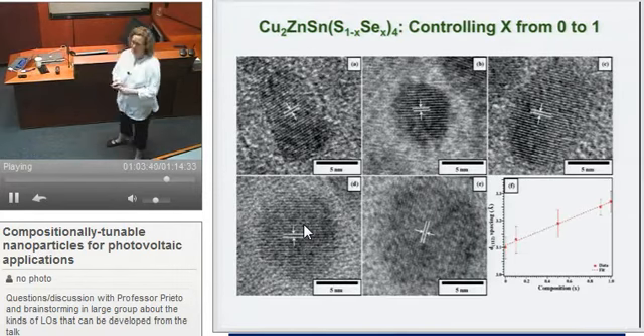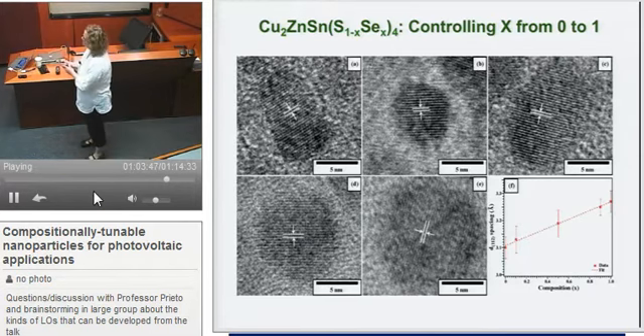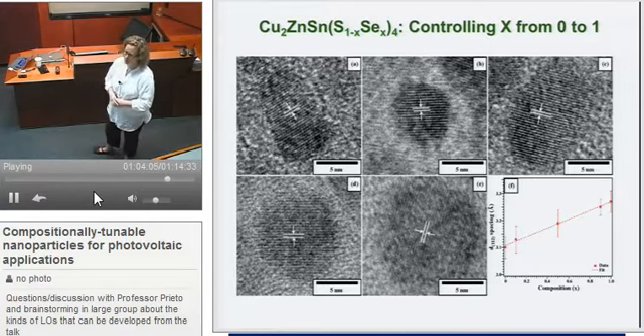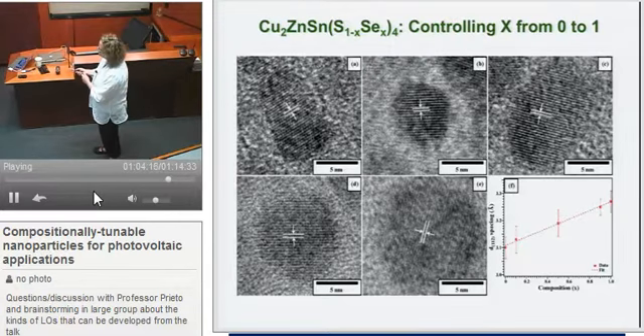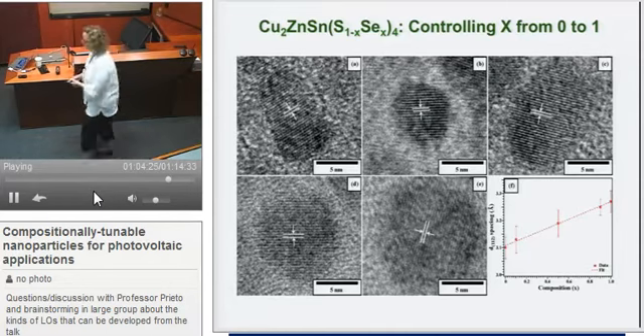Again, for all the reasons I showed you before regarding the powder patterns, I just wanted another method to corroborate this. So Shannon looked at nanoparticles of all the different compositions: 100% sulfur, then 10% selenium, 50, 90, 100% selenium. She measured the width of the lattice spacings, and this is where we did put error bars on things. She measured at least 100 particles from 3 different batches that were made on different days and from different bottles, just to make sure we were seeing something real. We fixated on the 112 lattice plane because that's common to both structures, and that's the one that varies linearly, and that's how we get these error bars.